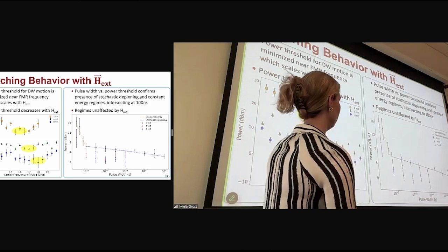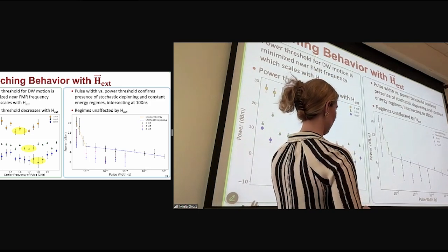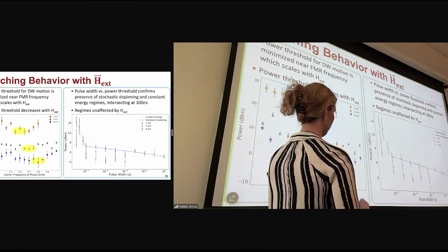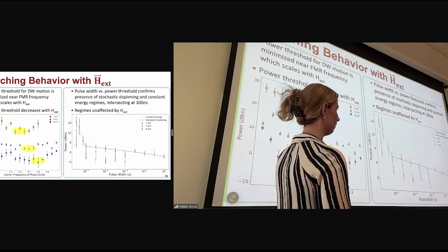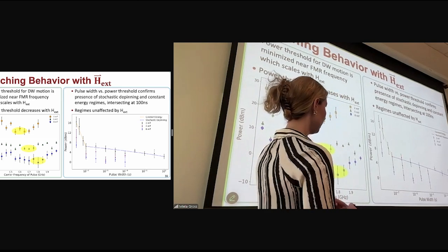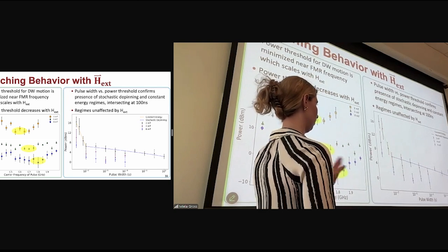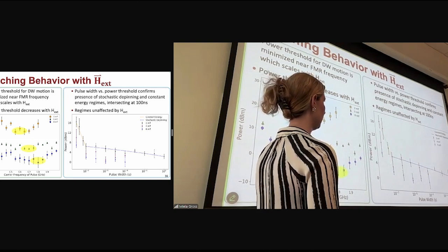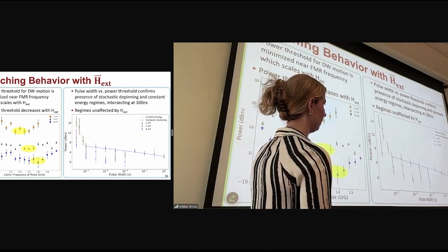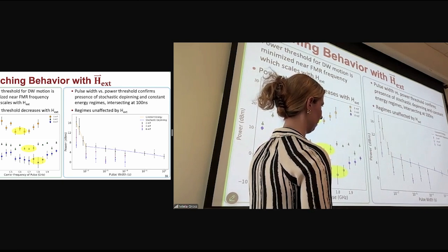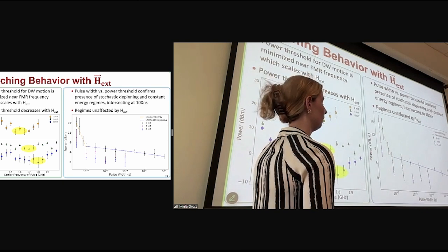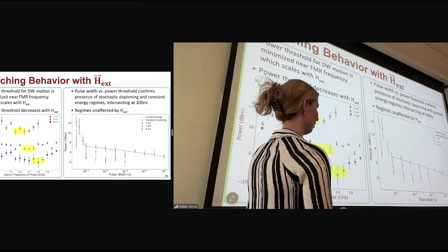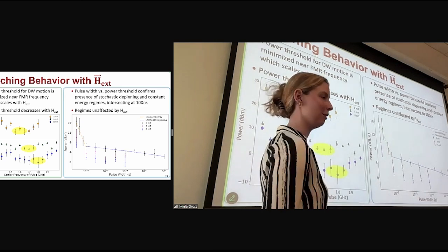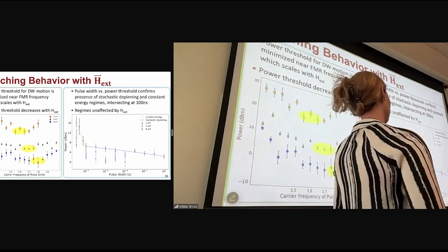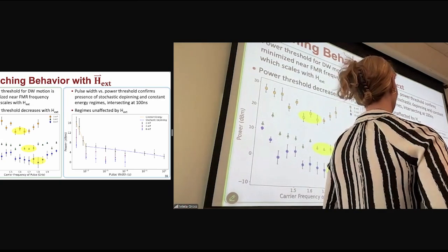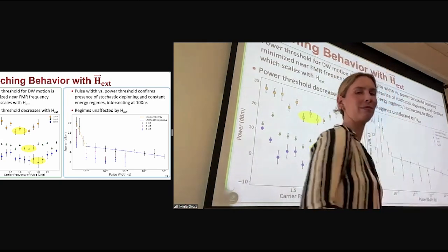Then if we move to the plot on the right, we see how pulse width again shows this constant energy versus stochastic depinning regimes. And they intersect similar to our past project around 100 nanoseconds. As we apply external fields, the external fields lower the power threshold needed to depin these domain walls. However, we don't really see a change in these regimes from the external fields.